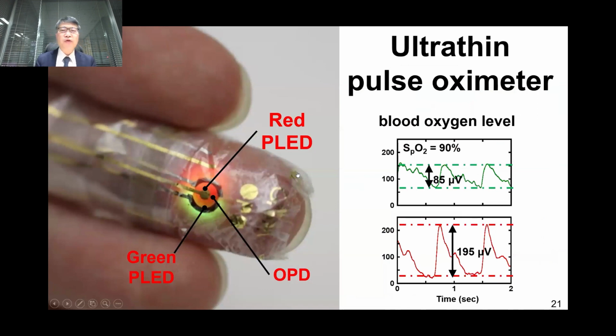One good example is the ultrathin pulse oximeter, where red and green LEDs are integrated with organic photodetectors. This device can be attached on the surface of the fingertip and obtains very stable physical contact. Thanks to the ultrathin film features, the sensor attachment doesn't cause any pain of wearing. And because an ultrathin film can establish good physical contact, it is quite resilient against motion artifacts.